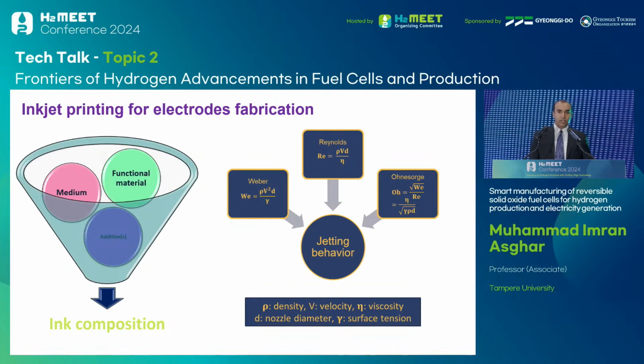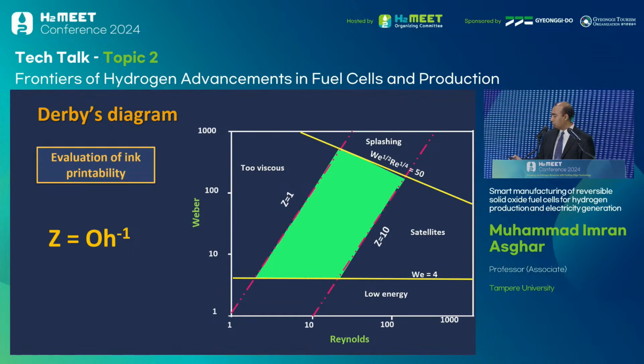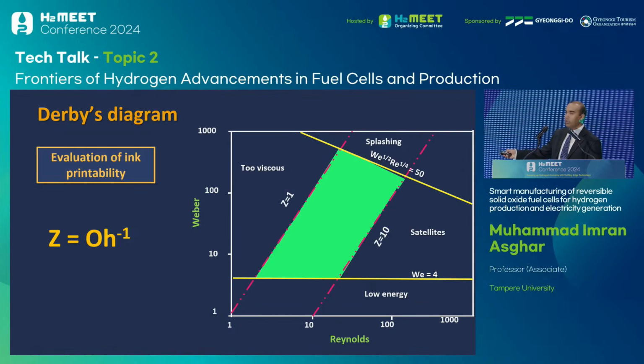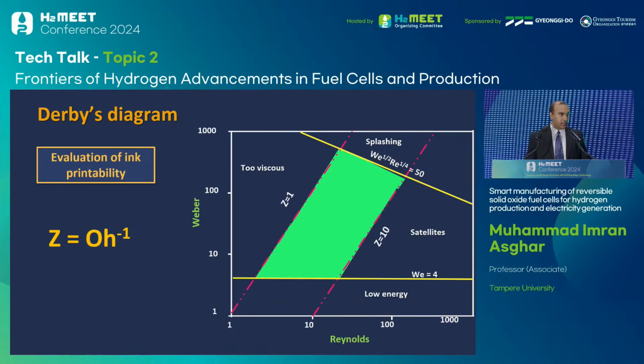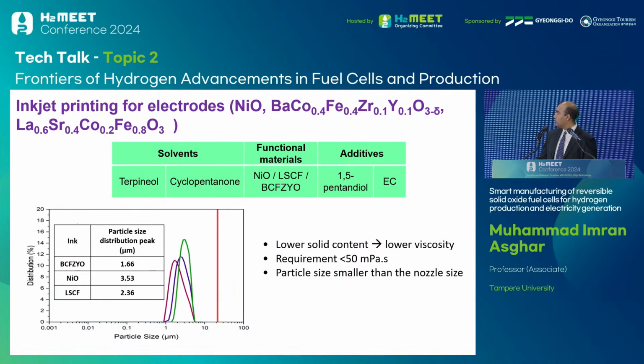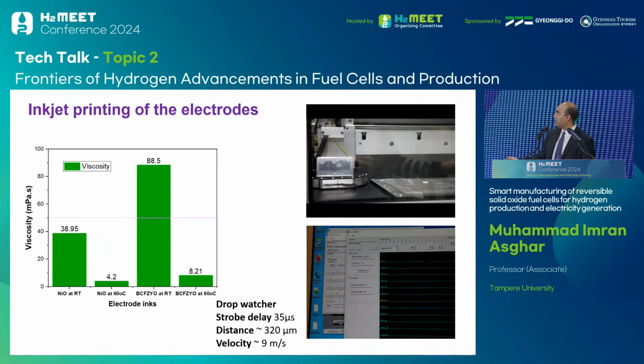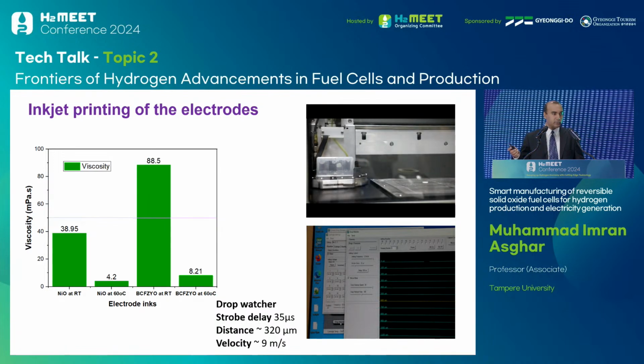Then once the electrolytes are ready, we prepare our electrodes by inkjet printing. For that, again, we have to do the ink formulation, and we have to calculate some numbers, the Weber number and also the Reynolds number. The quality of an ink is evaluated by this Derby's diagram. In the Derby's diagram, on the x-axis we have the Reynolds number, on the y-axis we have the Weber number. If your ink falls in the green region, it means that it has good ink printability. So in this particular case, I'm presenting our inks. First of all, we have to make sure that the particles in our inks are smaller than the nozzle size. Then they should have an acceptable viscosity.